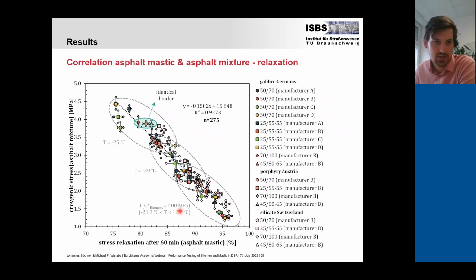Now we see very similar behavior on the asphalt mixture. So at low temperatures, we have very high cryogenic stresses in the mixture, and at higher temperatures, we have lower cryogenic stresses. And actually, we found a linear correlation between the stress relaxation from DSR and this cryogenic stress, where we also see the influence of the binder. So the softer binders, which are included here, so the legend is quite large since it's 18 different material variants.